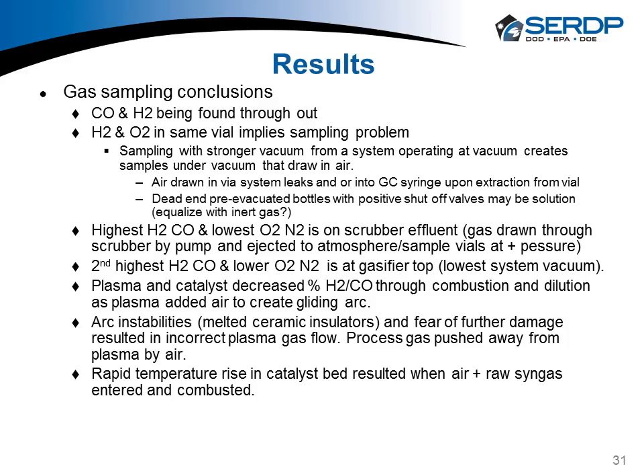So these GC mass spec samples are going to be under vacuum. It's going to tend to want to draw in air. We would immediately pull the syringe needles out in a manner that we didn't have a direct open path. We would disconnect from the process pipe, pulling the syringe out of the vial, and then immediately pull all the syringes out of the vials and cap them with an aluminum foil tape to try to seal them off as best we can. But I think part of the problem is if you have a gas sample at a vacuum and you do your GC mass spec or GC sampling with a syringe from that vial, the syringe is going to be at a vacuum as well. So when it withdraws from the vial, it's going to tend to want to draw in some air as well. So there's one thing learned the hard way.